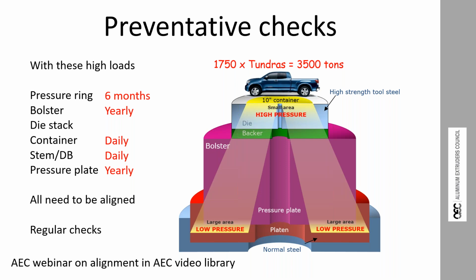The bolsters should be checked yearly, that they're not coined. We found a bolster that when we put a steel ruler over the flat face that was normally in contact with the backer, we could flick quarters underneath the ruler in the middle. The bolster had dished so much over years. And so I asked how long since this bolster was checked. And it turned out the bolster had been in the plant for 12 years and had never been looked at once. That's not a situation we really want. We need to make regular checks.